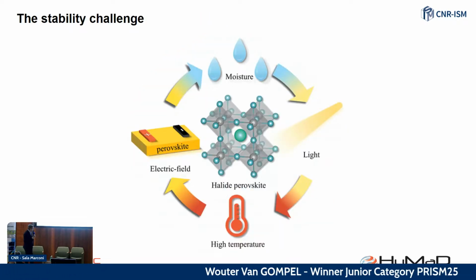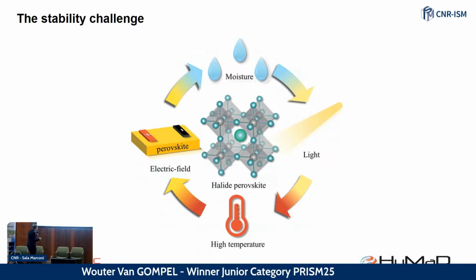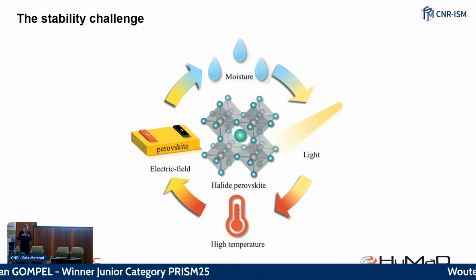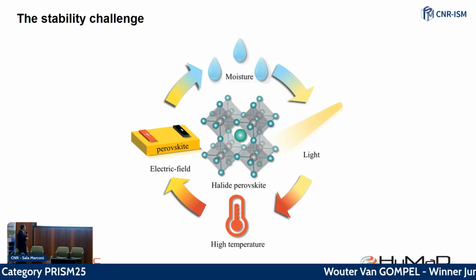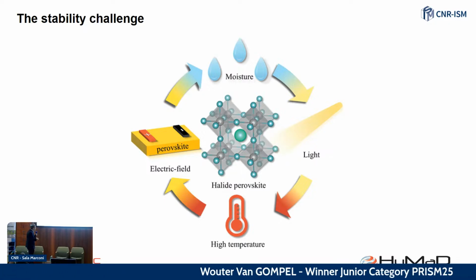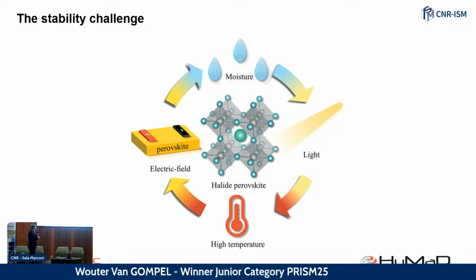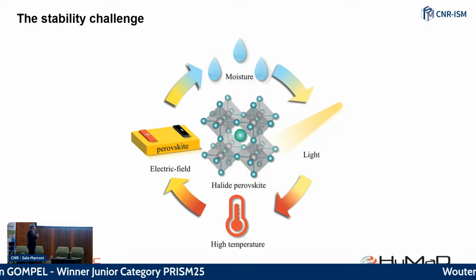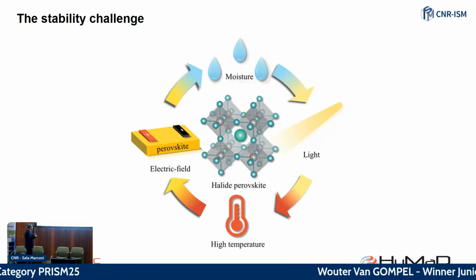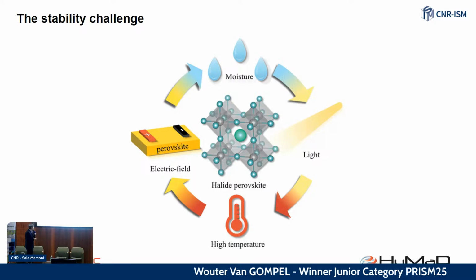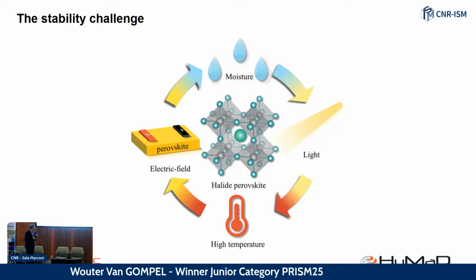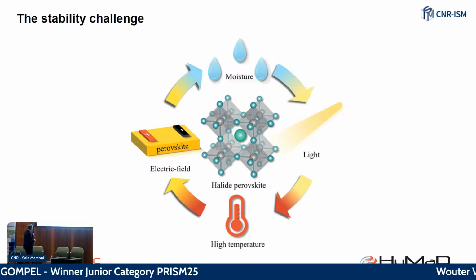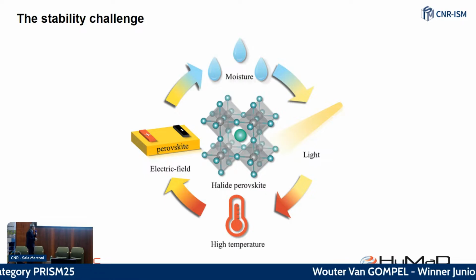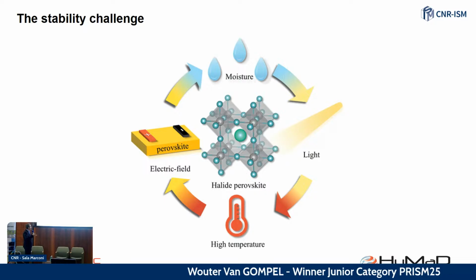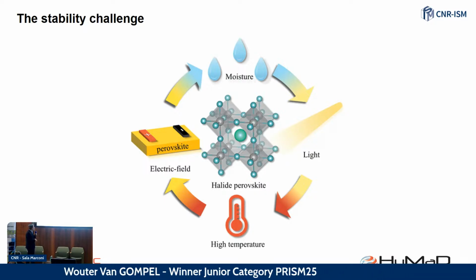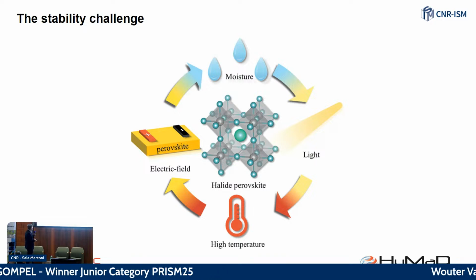There is one caveat, or there are a couple, but there is certainly a stability challenge because they are ionic materials. It's an ionic structure, this metal halide structure, which means that in general they are quite sensitive to influences of moisture, intense light, like intense lasers, high temperatures, and even electric fields, because these ions tend to be quite mobile. So that's one of the big challenges. Researchers over the years have, of course, improved the stability enormously. They were known as really, really unstable. But over the years, material development and encapsulation and things like that have really improved the stability enormously. But still, it remains a somewhat intrinsic challenge of some of these materials.